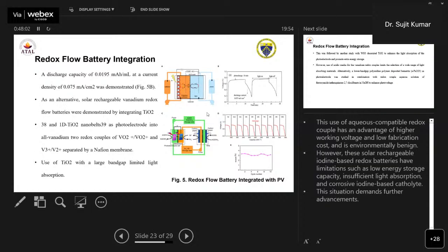In this figure B, you can see a discharge capacity of 0.0195 milliampere-hour per milliliter at a current density of 0.075 milliampere per centimeter square. Photo charging is around 0.6 in 10 minutes, and then for discharging, from 0 to 10 minutes the discharging rate was very low.